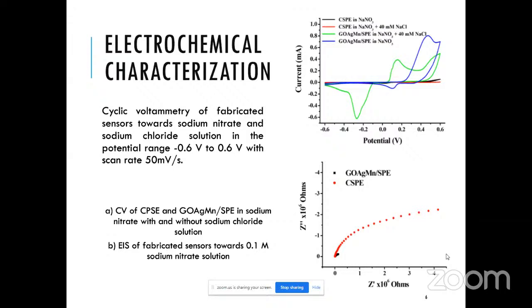And it can be seen that a Faradaic peak was recorded near 0.1 volt for the catalyst coated electrode in the presence of chloride ion. This is due to the conversion of silver species in the catalyst to silver chloride in the presence of chloride ions when the sample was introduced. This shows that the catalyst ink is electroactive towards chloride ion.